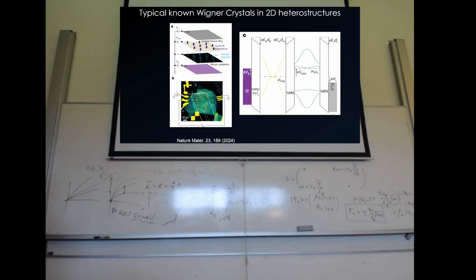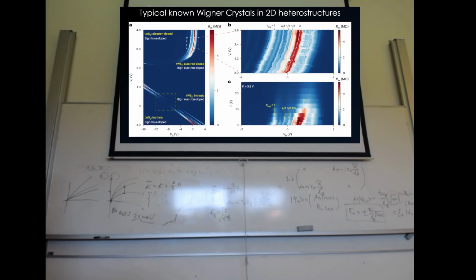And using this kind of system, you can do the coupling of another layer of bilayer graphene and this superpotential from the Wigner crystal. And indeed, you can see that there are lines of partial filling. That means you have a Moiré unit cell, but this Moiré unit cell is not from the lattice. It's purely from electronic interaction, and the size can be well defined, which is in very good agreement with transport evidence and the STM evidence.